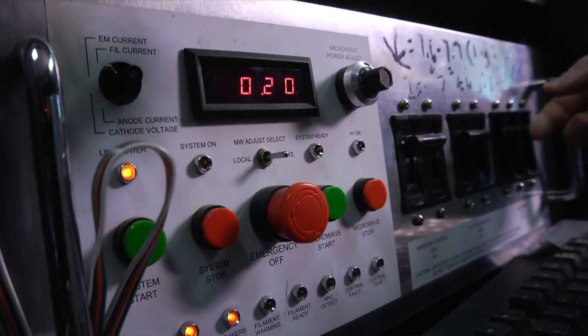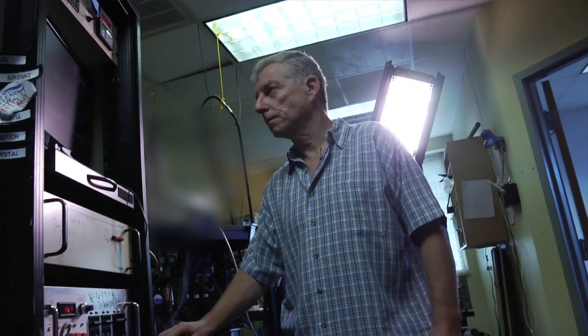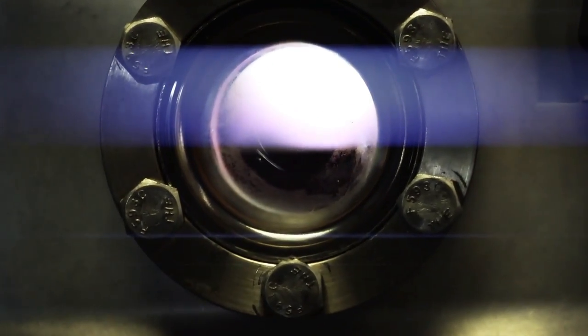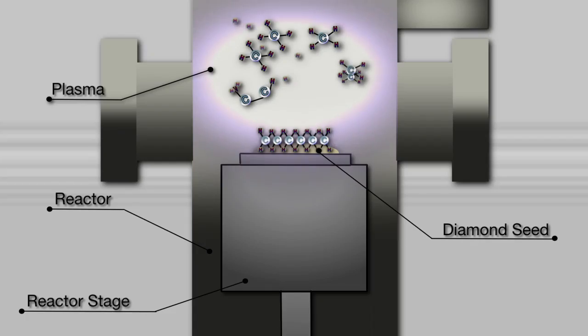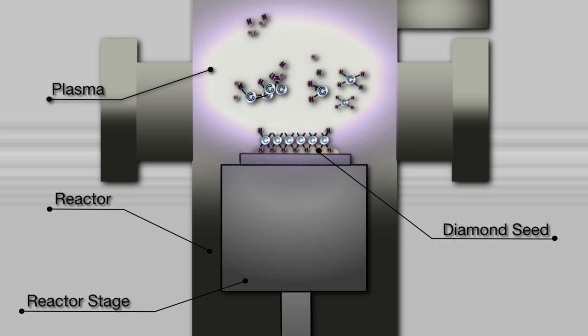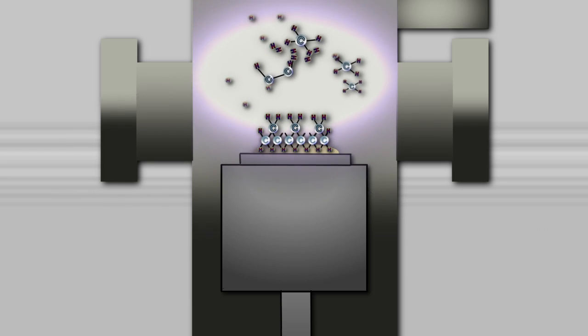The error there is that what we are doing is not using a pure carbon situation. We are actually using carbon with hydrogen. In our specific case, we use plasma to dissociate hydrogen to atomic hydrogen, and plasma is another state of matter entirely and is not normally represented in a phase diagram. We think the atomic hydrogen formed by the plasma is able to preferentially etch the graphitic bonds, thereby enabling the system to form diamond instead of graphite.